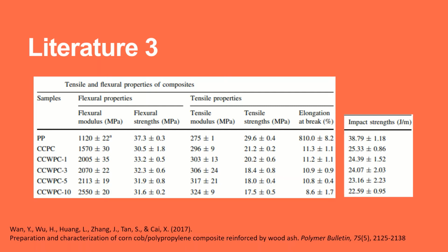However, when wood ash was added into the corn cob flour polypropylene composite, the flexural strength increased first and then decreased. This trend indicated that with loadings of 1 weight percent, wood ash might have a good dispersion, but wood ash would aggregate with higher content, which gave rise to the poor dispersion of wood ash.